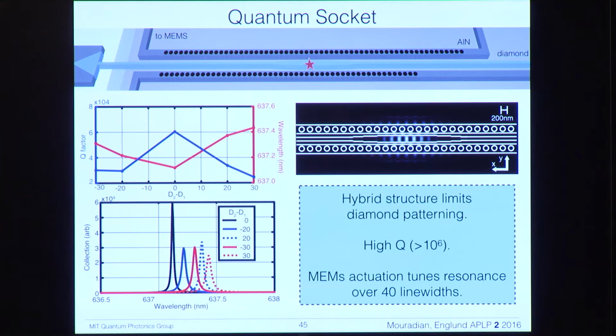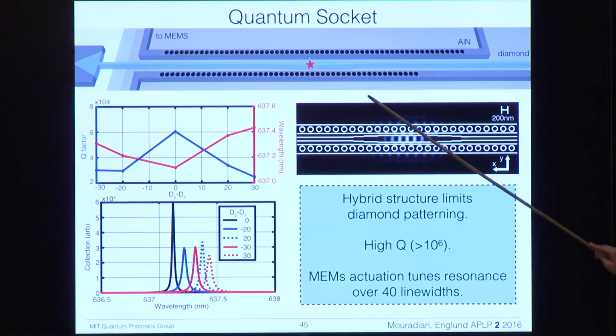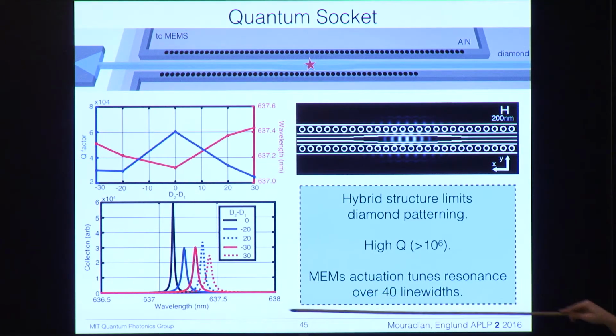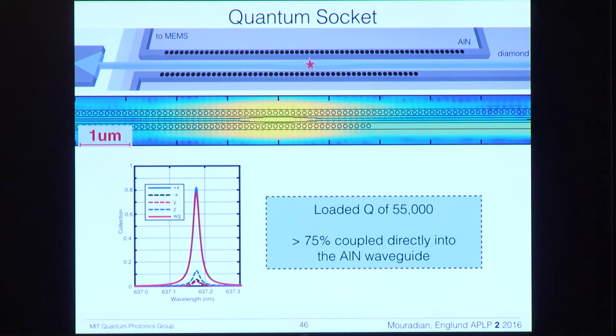So this is all in simulation, but as we move these two bars in and out, we're able to tune the resonance over 40 linewidths. In pure nanometers, that isn't much in this simulated structure. But if we want to sacrifice Q for tuning, we can create a lower Q device that is tunable over a larger overall nanometer range. And then we have direct connection into the underlying aluminum nitride photonic integrated circuit.